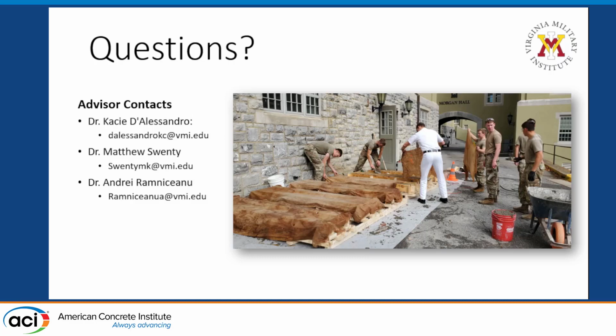Question: The laminate thickness that you're using is very thin, given that you're using steel fibers, and that seems like it might be too thin for the fibers to be placed well. Yes, sir. How big were our fibers? They're real thin. I would say length and I think 0.28 diameter. Yeah, but if they're half-inch long and you're doing a half-inch overlay, I believe they're about a quarter to maybe half of that thickness. But you're right. Thank you very much, sir. Maybe increasing that thickness could allow for those steel fibers to be used with more versatility.